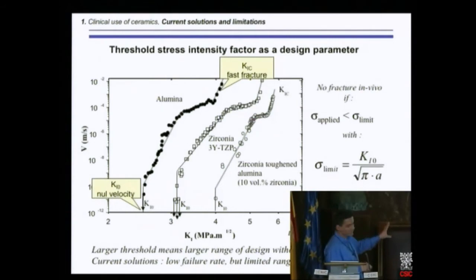We also investigated that aspect, and we said that it was important to investigate the threshold below which no crack growth should occur, and of course the toughness. But for delayed failure, what is more important is the threshold. And we can say that there will be no fracture at all, no risk of fracture, if the applied stress at the implant is everywhere lower than a limit, which is quite simple to calculate. This limit is given by the ratio of the threshold, KI0, upon the square root of the crack size. So we can play a role on the process, because the crack size is here, and we can play a role, and we have shown that before, on the threshold below which no crack growth occurs.